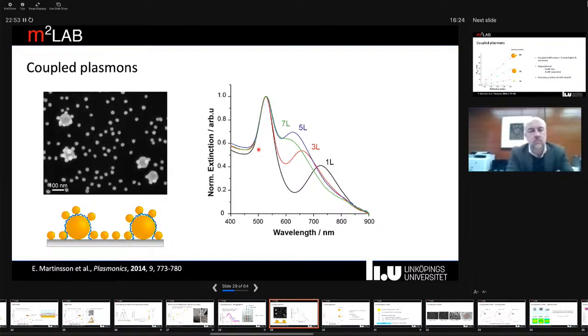And we can see that going from one very distinct plasmon band, this splits up into several different plasmon modes due to this plasmonic coupling. And we can see that we redshift the second plasmon mode more the closer the particles are to each other. So with just one polymer layer, we have a very well-defined second plasmon band that we can use for sensing.